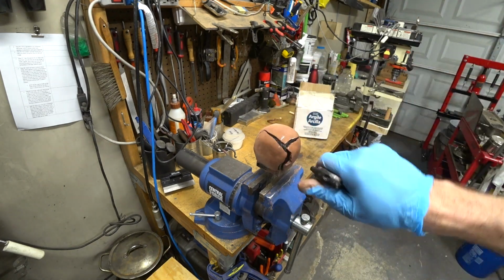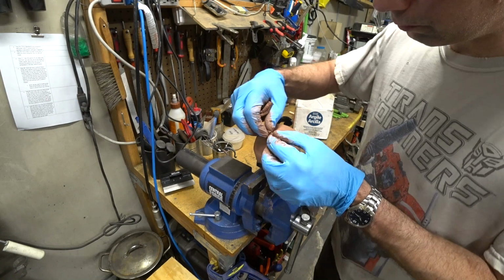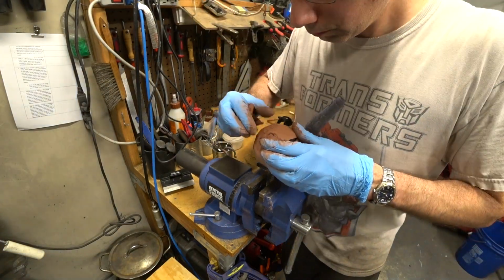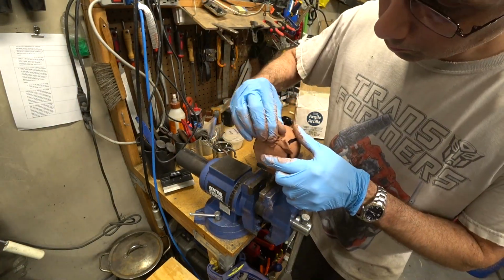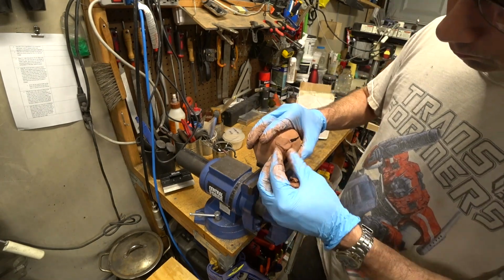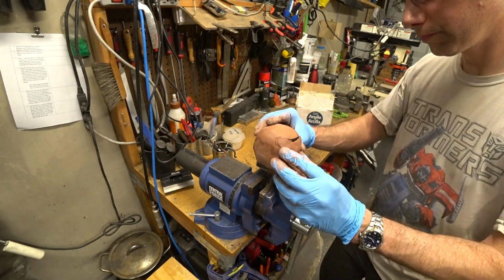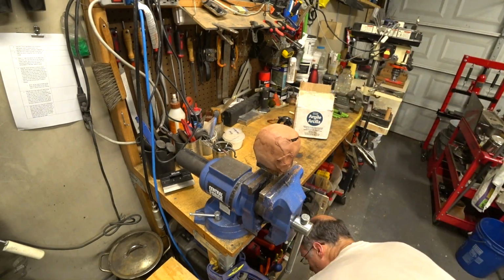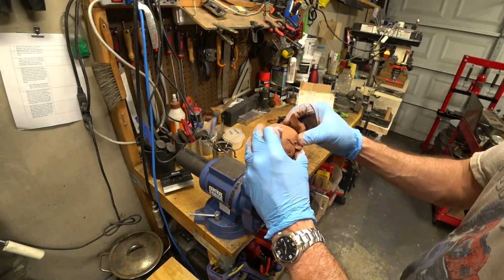Now, it would have cracked less if I let it dry without using the oven. And I also forgot to add any grog to the clay. Adding about 20% sand to the clay before I put it on would have made it crack much less.